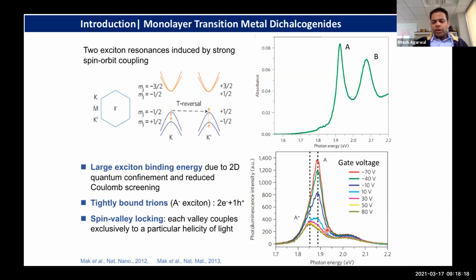And when you go down to a monolayer, in the monolayer limit, you have time reversal symmetry because these are non-magnetic systems, but inversion symmetry is broken. So the two valleys at K and K prime, and this becomes important for some part of my talk. One can address these otherwise degenerate valleys at K and K prime uniquely via circularly polarized light. So if you have one circular polarization, you excite carriers only in one valley, and the opposite circular polarization excites carriers in the other valley, leading to what is called valleytronics.